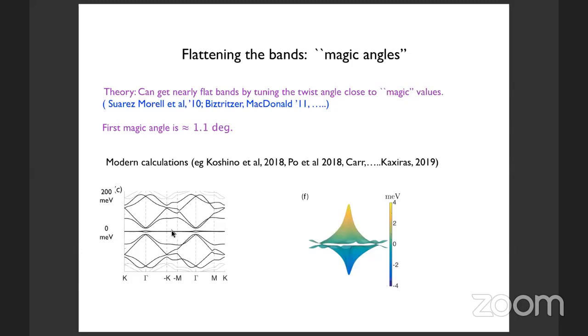If I blow up this tiny region, I get this plot on the right, where the width goes from 4 millielectron volts to minus 4 millielectron volts. On the big scale on the left, you hardly resolve it. You see that there's some dispersion, some band structure, so it's not exactly flat, but the bandwidth is only about 8 millielectron volts or so, much narrower than the bandwidth of ordinary monolayer graphene, which is on an electron volt scale.